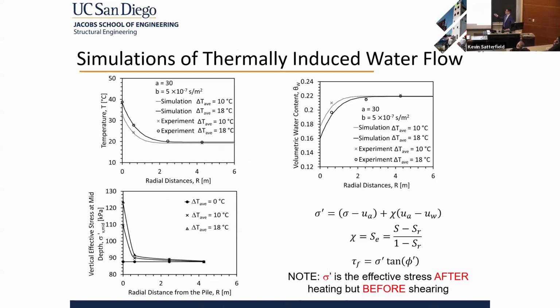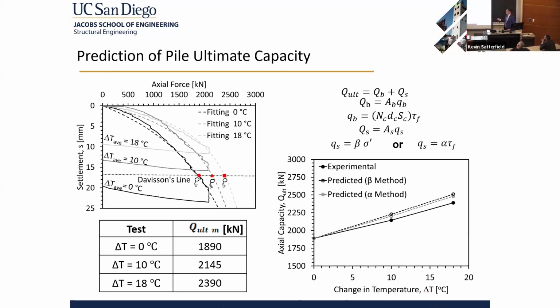And as you see, when you heat the soil by 10, by 18, it causes the water content to decrease right at the pile interface, and that causes the effective stress to significantly increase right at the pile interface. I'm a big advocate of using effective stress for unsaturated soils because you can consider both suction effects as well as degree of saturation effects. So now that we know that the effective stress is increasing at the pile interface during heating, we can put that into a load transfer ultimate capacity analysis, and we were able to get very good predictions of our ultimate capacity as the pile is heated.